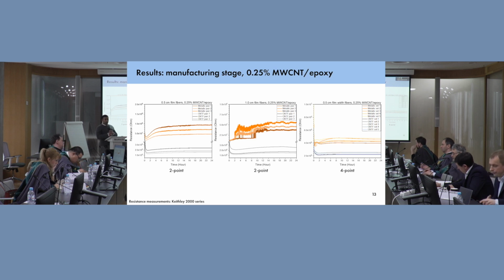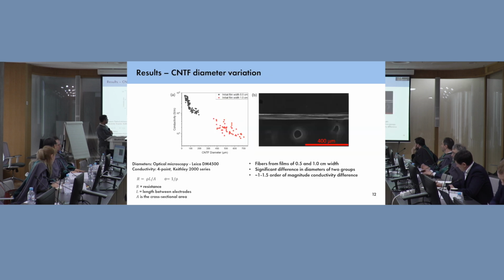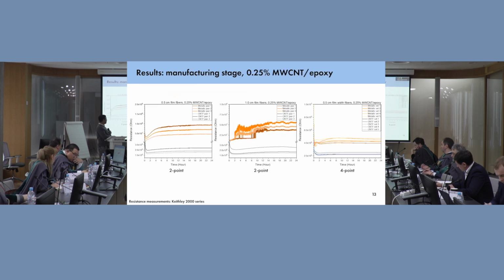Now, we did 2-point and 4-point. As I mentioned earlier, we used thicker fibers and thinner fibers. The first image on your screen is from the thinner fibers. The second one is from thicker fibers. And as we can notice, the resistance during manufacturing is very, very similar. So if we just look at the diameter difference, it's quite large. It's about 3 to 7 times in cases. So we do not see any effect here.